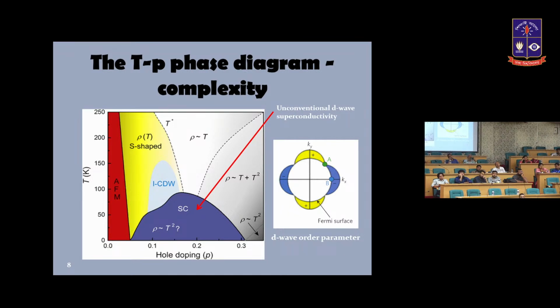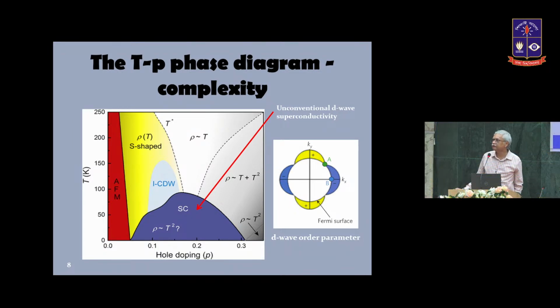In addition to many exotic properties in the normal state and in the superconducting state, you also have a d-wave order parameter. The order parameter changes sign within the Brillouin zone, and there are places where the superconducting gap vanishes. These are called the nodal points. At the antinodal points, these points, you have the maximum of the superconducting gap. In ordinary superconductors, which we call BCS superconductors, the order parameter is s-wave-like, that is spherically symmetric. But for copper oxides, the order parameter has different symmetry.